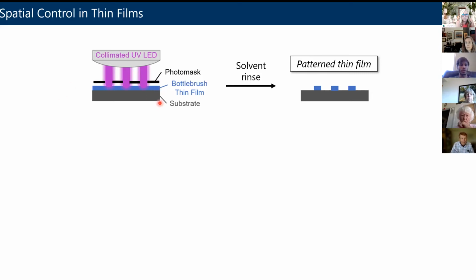What you do is take your substrate, like a silicon wafer. You can coat a thin layer of the Bottlebrush polymer on top. This is the uncross-linked material, just the as synthesized viscous liquid. And you take a mask, which is dark in some regions and transparent in other regions, and you shine light through that mask. You can make the mask have a pattern, meaning the transparent regions have different shapes that you can control. Where the light hits the Bottlebrush thin film, it cross-links like we've seen before, because there's a little bit of benzophenone in there. Where it doesn't hit the film, no reaction.